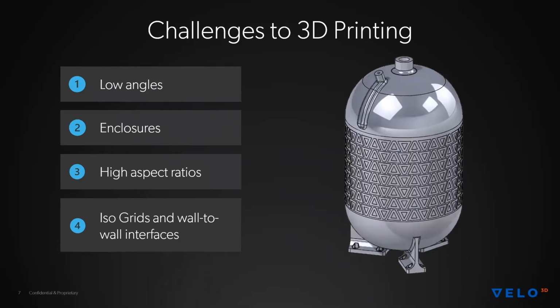So what are the challenges with 3D printing of these specific pressure vessels? First and foremost, you have low angles. And printing of low angles, we all know, is Velo's claim to fame. It's what we do best. And inside these enclosures, if you add support material, you can't really get it out. Oftentimes it's extremely difficult or nearly impossible to get out this added support material. And it's a catch-22 on an incumbent metal 3D printer. For these low angles, you need to add support material, but you can't get it out. Velo3D just doesn't need to add support material on the inside of this part, so it's printed completely support-free.